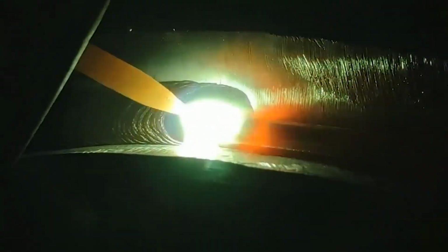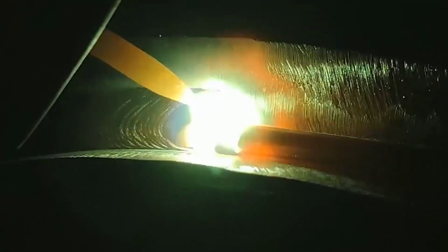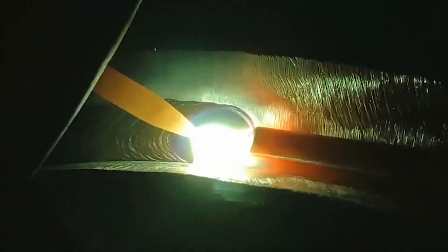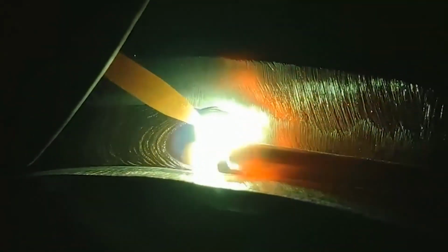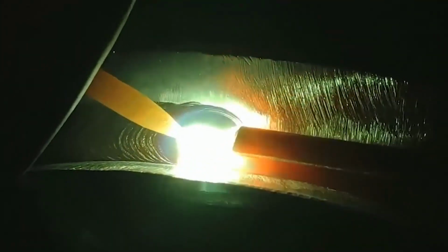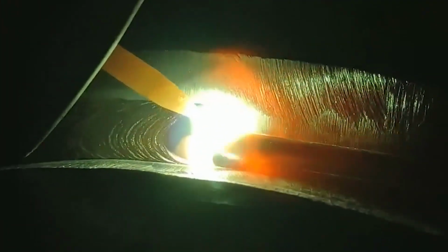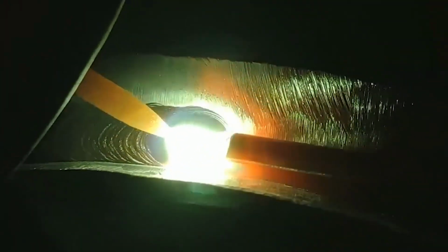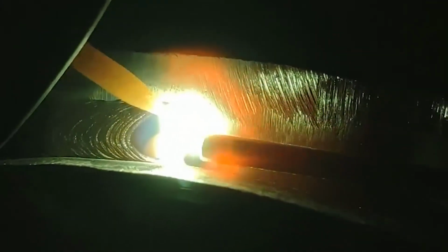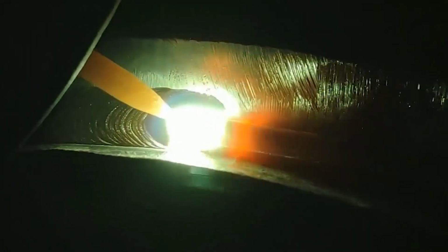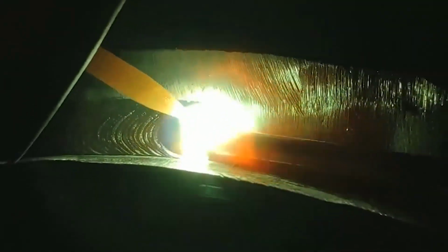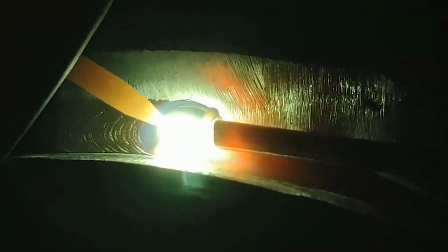In argon arc welding, the relative positions of the welding torch, filler metal, and weldment are as follows. The arc length is generally 1 to 1.5 times the diameter of the tungsten electrode. When stopping welding, first extract the filler metal from the molten pool. Filler metal is added according to the thickness of the weldment, and the hot end still needs to stay under the protection of argon gas flow to prevent its oxidation.